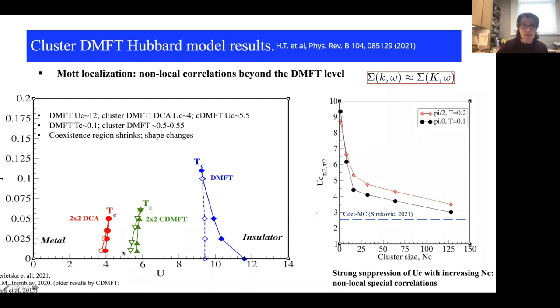So we can see that including short range correlation, or going beyond the single-site local approximation, the critical value of U at which the metal-insulator transition occurs is significantly suppressed. The same suppression is observed for the critical temperature TC, and the coexistence region is shrinking. Okay, so we do see a significant effect of non-local correlation on the metal-insulator transition for the Hubbard model. Recently, we have been working on going beyond the 2 by 2 cluster with DCA and going for much larger clusters. On the right, I'm showing you results obtained for temperature 0.1 as a function of cluster size. We see there is a strong suppression of the critical value of U as we increase cluster size.